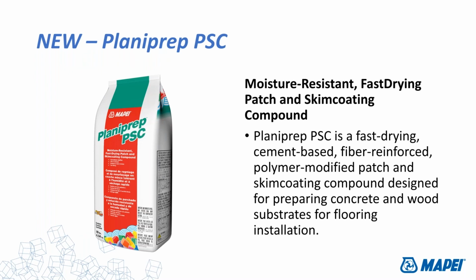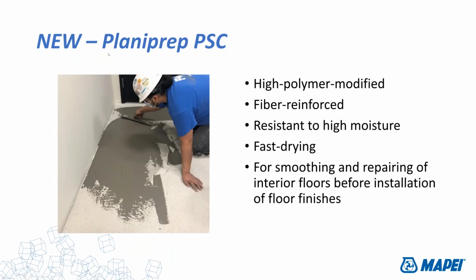A new one we just introduced is Planiprep PSC, Patch and Skim Coat. Here is now another solution for floor prep in a high moisture condition. It is a fast drying product that can be feather edged and goes up to a 1 inch fill thickness. We'll put all this in a chart at the end to make sure you get all that information. But Planiprep PSC is a very nice troweling material, high polymer modified, fiber reinforced, resistant to high moisture, fast drying. I think you'll be quite pleased when you look at the drying data that we present in a little bit, and definitely for smoothing and repairing interior floors on high moisture concrete slabs.